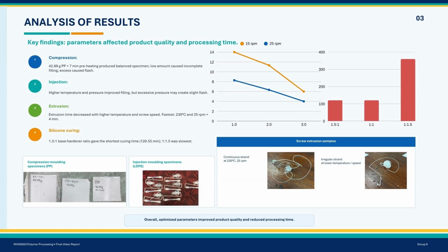For the curing test, the 1.5:1 ratio recorded the shortest curing time, while the 1:1.5 ratio required the longest time. This indicates that the base to hardener ratio influenced the cross-linking process and curing behavior. Therefore, selecting the optimum processing parameters is essential to improve production efficiency.